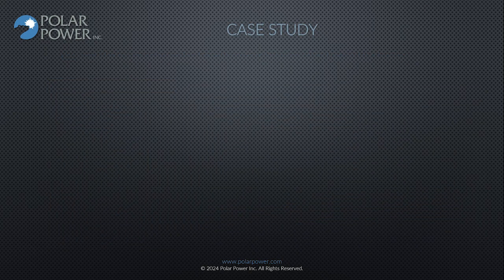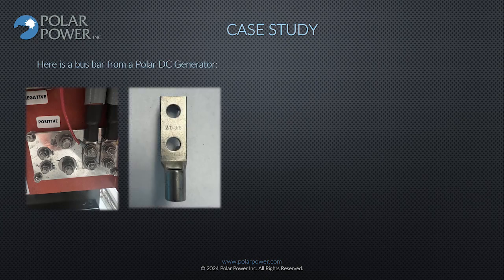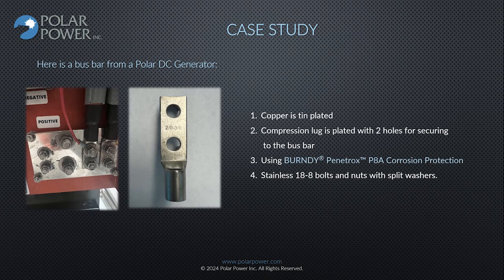Here is a bus bar from a Polar DC generator. Copper is tin plated. Compression lug is plated with 2 holes for securing it to the bus bar. Using Burndy Penetrox P8A corrosion protection. Stainless 18-8 bolts and nuts with split washers.